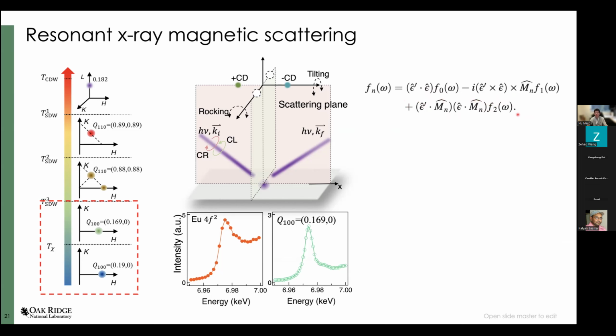So most of the time when we talk about resonant X-ray magnetic scattering, we only focus on this term. For this particular situation, since we have a single-Q helical spin density wave, we can calculate the circular dichroism analytically. I will skip all the detailed calculation. Basically, for a single-Q helical spin density wave, your circular dichroism is proportional to tau and chi. Here, chi is your chirality. Tau is a number that's related to your wave vector.